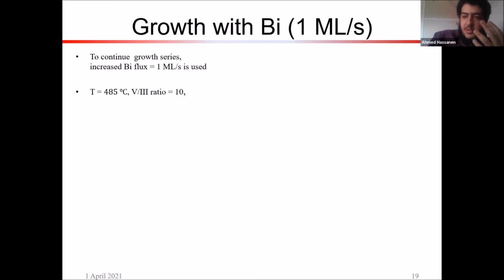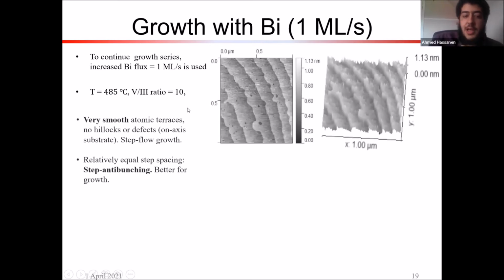And so naturally, we wanted to increase the bismuth flux to see if we're going to get smoother surfaces. And so we continue this growth series with bismuth flux of 1 monolayer per second this time, rather than 0.4 monolayers in the previous slide, with same temperature. And what we get is even smoother surfaces. So bismuth is indeed really inducing these smooth surfaces and getting rid of these hillocks. And so we get these very smooth atomic terraces with no hillocks. And again, this phenomenon of step flow growth. And these steps have relatively equal spacing, as you can see here, they're relatively even. And this is a phenomenon known as step anti-bunching.